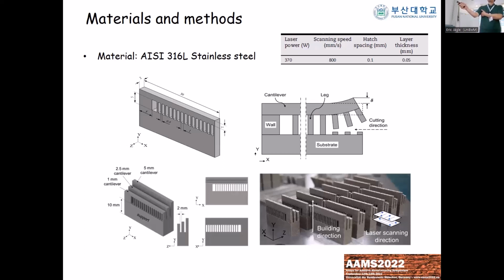But as soon as we print the first layer, the second layer will shrink, and then there will be some force balance between the first and second layer, again and again. And finally, we have developed a complex residual stress. Afterward, when we cut, there will be some distortion of the cantilever. By calculating the residual stress and calibrating the model with this distortion, we can figure out how much residual stress it is. For better calibration, we have used 3 different thicknesses of the cantilever, and we have modularized this for easy heat treatment.